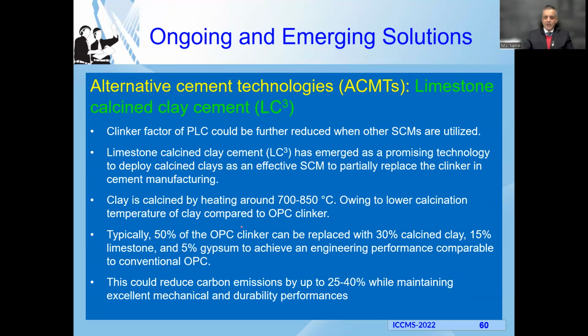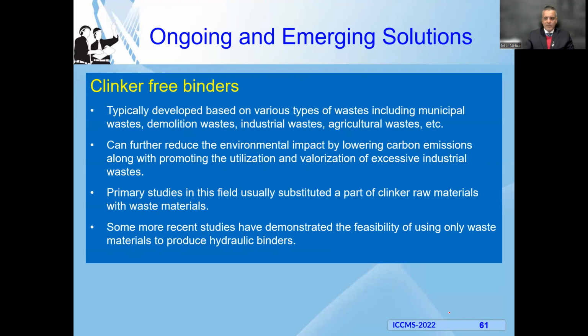The use of limestone in cement could be beneficiated much more significantly when coupled with supplementary cementitious materials, most notably with calcined clays. And I'm sure you heard about the LC3 cement and the work of Karen Scrivener in Switzerland around this, and many other researchers, where we could replace maybe 50% of ordinary Portland cement clinker, with something around 30% of calcined clay, 15% limestone, and maybe 5% gypsum, and attain engineering properties that are quite comparable to ordinary Portland cement, and allowing us to reduce, depending on the composition, somewhere around 25% to 40%, maybe even 50% of CO2 emissions while maintaining excellent mechanical and durability performances.